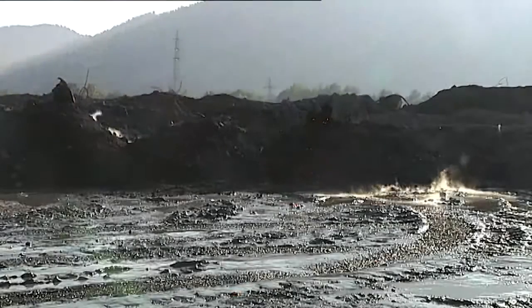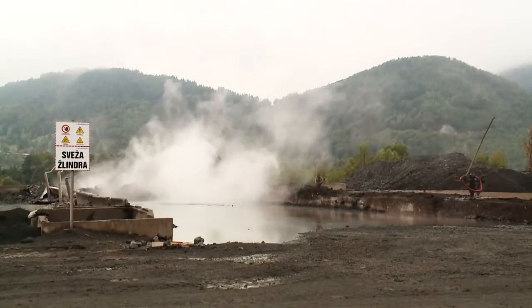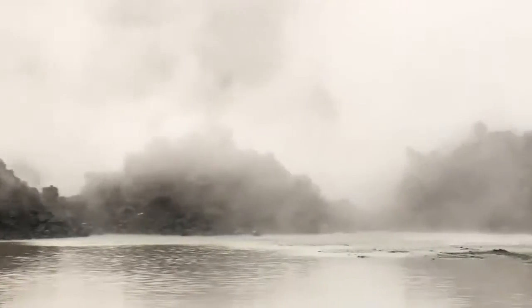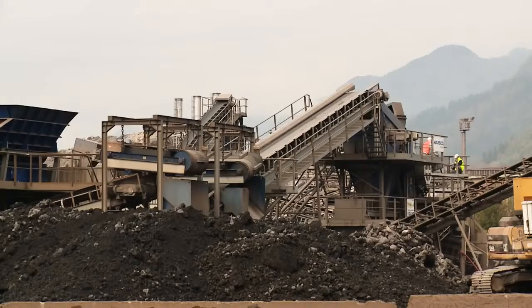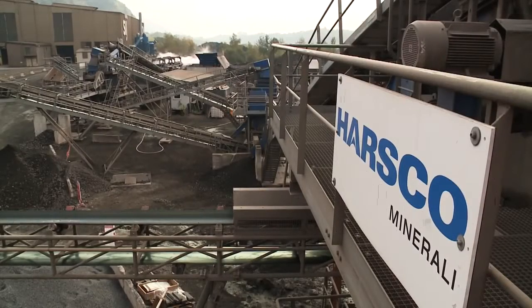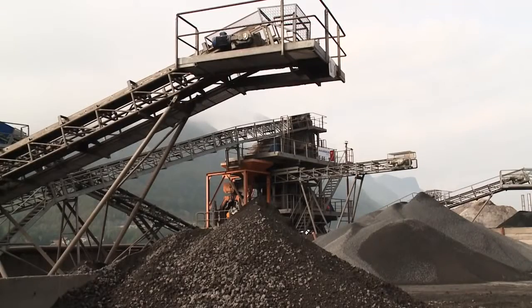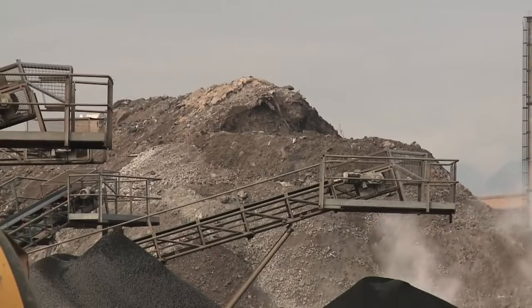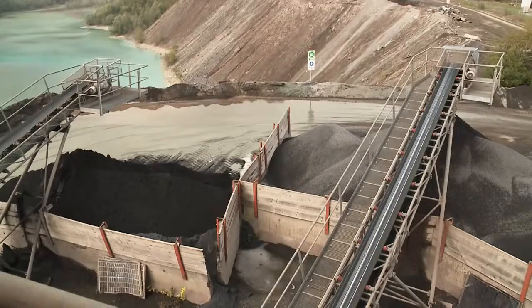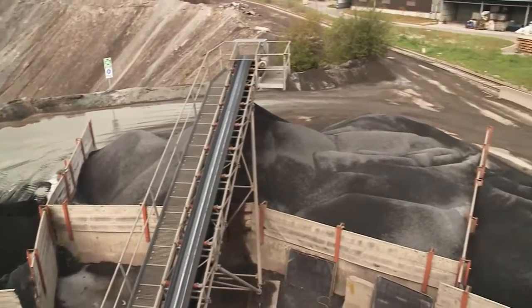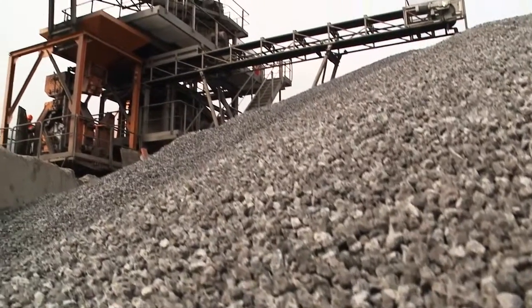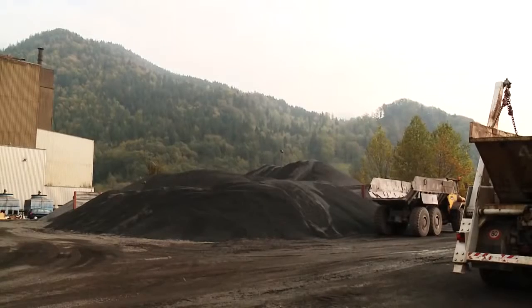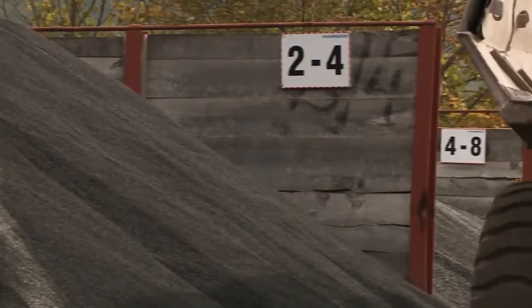Here the first stage of the aging of the slag takes place, which consists of 2 weeks of wetting and mixing. In this way the slag cools down slowly and in a controlled fashion, and its suitable microstructure is achieved. A transition of the unstable minerals into stable forms also takes place. The cooled slag is then moved to a more distant waste depot, where it is left to age for a further 30 days. The method by which aggregate is obtained from slag is similar to the method for obtaining aggregate from natural stone materials. 2 stages of crushing are needed, the difference between them being that the slag goes through a separate process of magnetic separation, where iron is removed in 2 stages. The crushed material is then sieved on standard sieves in order to obtain different sizes of granulations.